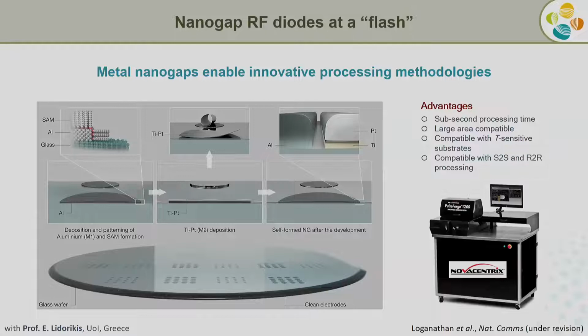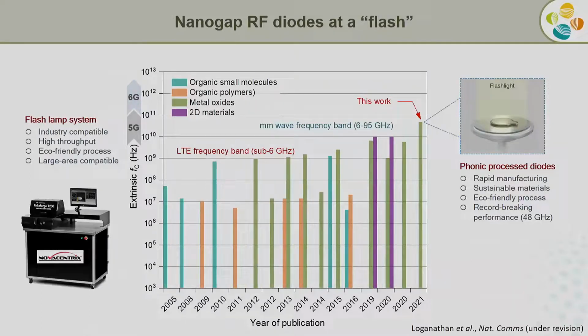And what this little distance between electrodes allows you to do is create devices which are very fast. One of the key parameters is the operating frequency, how fast you can switch these devices on and off. And this is gigahertz. 1 gigahertz is 1 billion times a second. And if you can reach 5 gigahertz, you're already in the 5G telecommunication spectrum. Suddenly, your technology becomes relevant to 5G devices. And if you push it beyond 90 gigahertz, you're entering 6G, what will be coming in 10 years from now. So suddenly we have large area footprint devices, and the way we manufacture them can make a big difference in terms of performance. Suddenly we don't need the expensive equipment the silicon industry has been utilizing over the years. So what are we doing now?